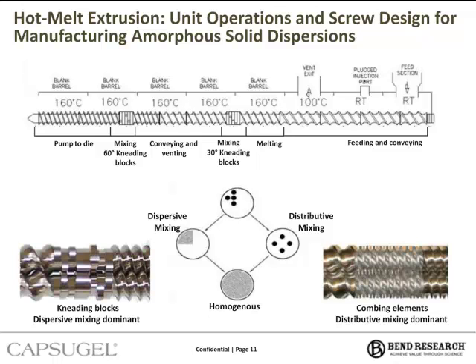Now, there's a cartoon in the middle that kind of shows the difference between the 2 mixing regimes. As we can see for dispersive mixing, we're taking the black dots in the top of the diamond, and we're further breaking those down to very small domains. Whereas in the distributive mixing, we're just distributing those equally within the space. Now, distributive mixing, we will use combing elements, and those can be seen on the right-hand side of the slide. Also, as alluded to earlier, the small angle kneading blocks have a lot of distributive mixing as well.